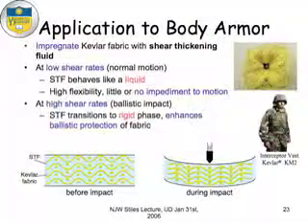And let me tell you a little bit about the story of what we did. The idea then is to take these fluids, which turn from a liquid to a solid under high rates of deformation or stress, and to make a composite material. Composites, by definition, are things where you can use two or more materials and get more from them, so that the whole is better than the sum of its parts. So by integrating a shear thickening fluid into a composite, we could take, for example, a known ballistic material like Kevlar, which works very well against some threats, and impregnate it with the shear thickening fluid, stop bullets, and make materials from it.